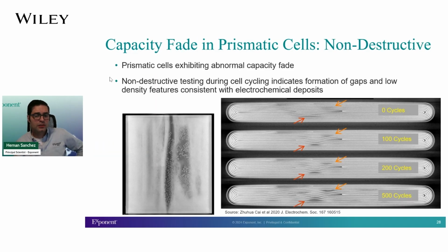That actually was the thought process we had back in 2020 when we prepared this paper on prismatic cells. We were observing some gaps in the as-made cells, but we also hadn't realized that as you were cycling the cells, those gaps became bigger. And as those gaps became bigger, you started to see these low density features consistent with electrochemical deposits on the cells when fully charged. Now, once again, the non-destructive tells you that this might be a problem, but you need the destructive testing to really push a little bit further and understand better what was happening.